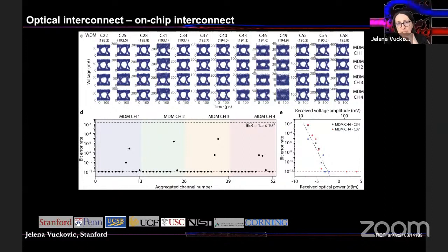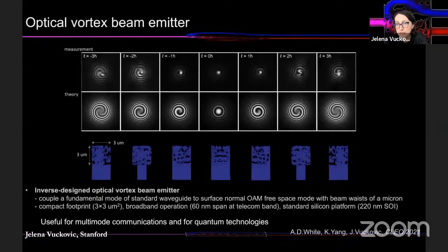And what we did here was measurement of the total communication rate, which is approaching terabit per second, and has an extremely low error rate, 10 to minus 12, right? So it's like 1 in every 10 to 12 bits would be erroneous without any error correction. So that's actually extremely important for these practical systems, and we're quite excited about it. And we also showed that we could actually do it for chip-to-chip configuration by using specialized fibers made by Corning and our collaborator, Dan Marom from the Hebrew University of Jerusalem.